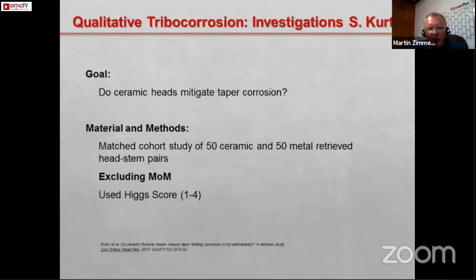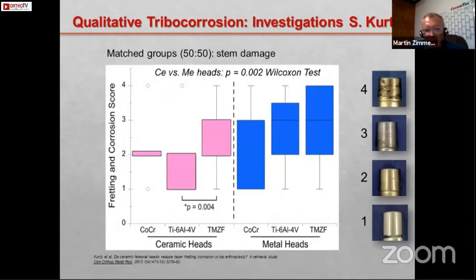For that, we concentrate on one of the first publications by Steve Kurtz, specifically on the retrieval analysis of 50 ceramic ball heads and 50 metallic ball heads in matched pair patients. We excluded the metal-on-metal, and we wanted to see exactly what happened in this situation. So they used what we call the Higgs score, which is a qualitative scoring system that you can see on the right-hand side. Notice 1 to 4, 1 being no fretting corrosion, 2 mild fretting corrosion, 3 moderate, and 4 severe. And this is now represented on this graphic with the axis 1 to 4. And what you can see is two groups. On the pink side are the retrievals found with the ceramic ball heads, and the blue side with the cobalt chrome ball heads. So if you look just at the average, you can see that the blue is higher on average than the pink one. You see qualitatively there was more fretting corrosion observed using metallic heads than ceramic heads.